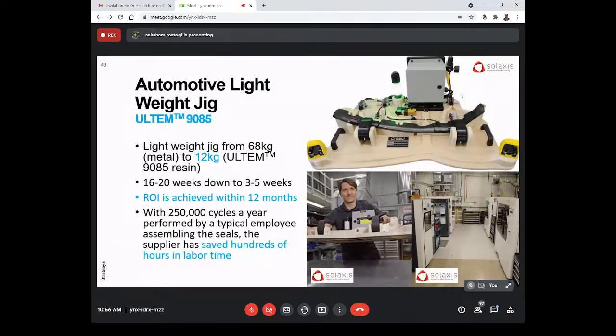this one company, Solaxis. They have replaced the metal fixture which weighs around 68 kgs with a 12 kg final fixture tool using the FDM solution. They're able to reduce their lead time from 16 to 20 weeks to 3 to 5 weeks. And they're also able to achieve their ROI within 12 months.